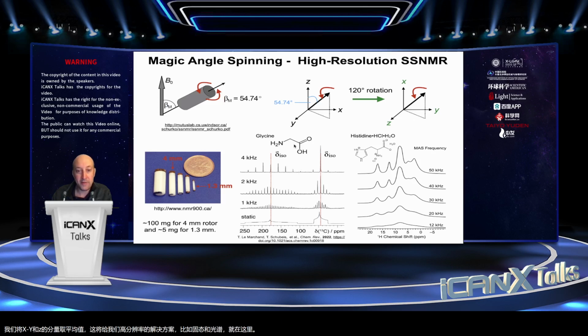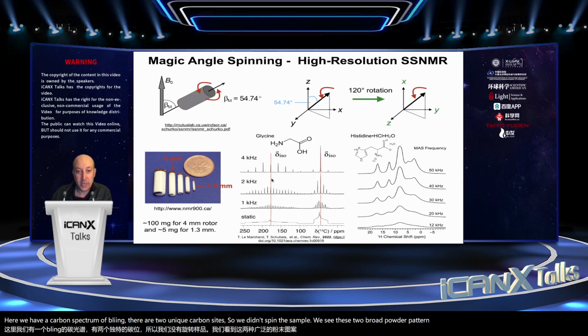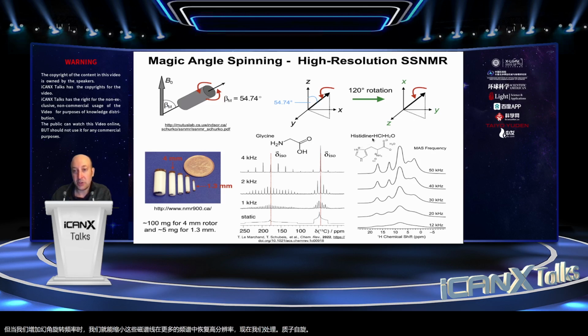Here we have a carbon spectrum of glycine. There are two unique carbon sites. So if we didn't spin the sample, we'd see these two broad powder patterns. But as we increase the magic angle spinning frequency, we're able to narrow up these NMR lines and recover a high resolution NMR spectrum. Now, when we deal with proton spins, they have very strong homonuclear dipolar couplings.